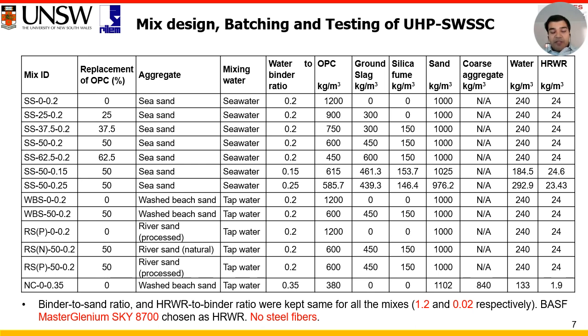So, we have developed several mixes in the lab, the parameters being replacement of OPC up to 62.5% by slag and silica fume, different sources of aggregate, and water to binder ratio. However, to keep things simpler, in this presentation, we will only evaluate 4 mixes. 3 of them are seawater sea sand ultra high performance concrete. Number 1, 100% OPC based control mix. Number 2, OPC and slag based binary mix. Number 3, OPC slag silica fume based trinary mix. And for comparison purposes, we will also discuss one conventional ultra high performance mix that is developed from natural water and natural river sand.